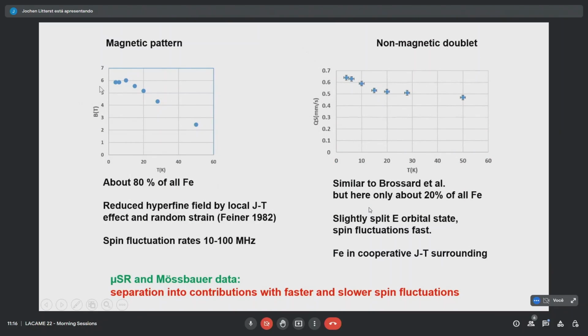We still have some problems here, so that may be some impurities, but you see the fits work quite nicely here at low temperature. It's now also a combination of magnetic and non-magnetic. So it's separate, as we see also in the muons. The magnetic pattern will have a saturation at a very low field only. That's actually explained by a paper of Feiner already in 82, who explained that in a Jahn-Teller system, the fields may be dramatically reduced, therefore we only see a small field.